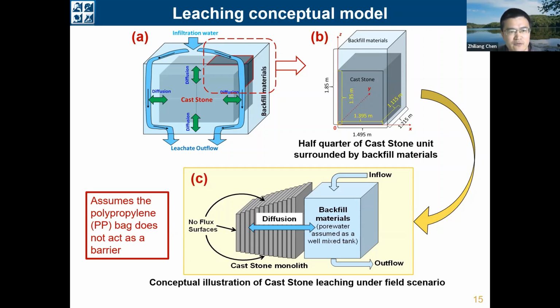And by taking a half of this unit, we further develop a reactive mass transfer model as shown in Figure C at the bottom. So in this figure, you can see on the left is the Cast Stone monolith, and on the right is the backfill material with the flow of the infiltration water. And during the flow of this water, contaminants diffuse from the Cast Stone monolith into this backfill material. And for conservative assumption, the polypropylene bag around the Cast Stone blocks is assumed not to act as a barrier for contaminants release.